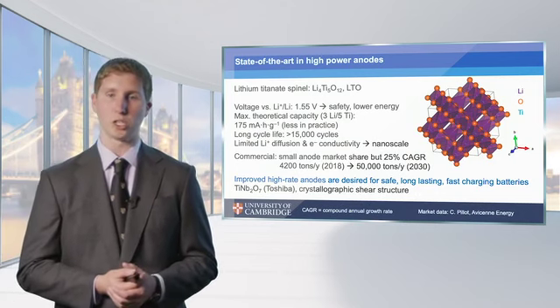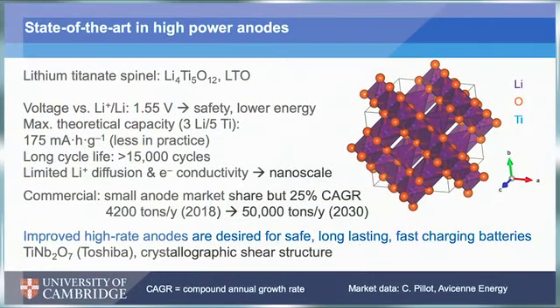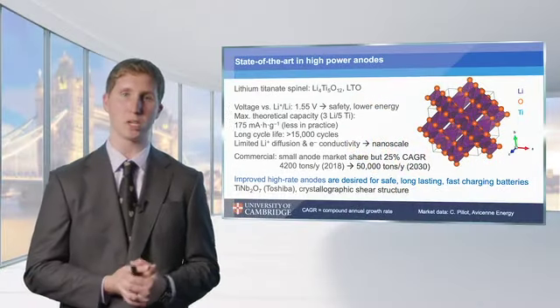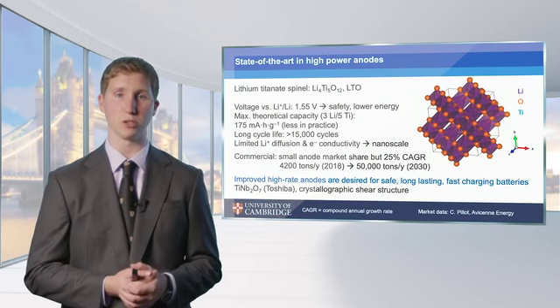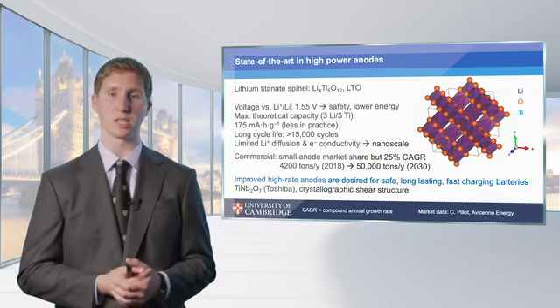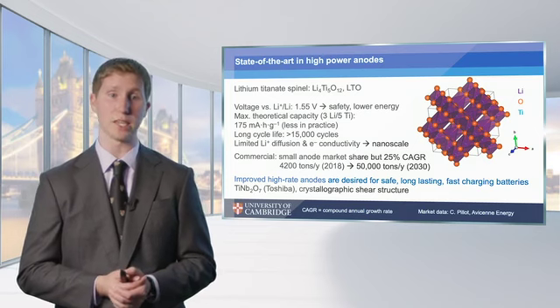Now, there is a small couple percent of the market currently which does utilize a material for high power and for fast charging applications, and that's the lithium titanate spinel. This material has a much higher voltage than graphite, and being the anode, that means it has a lower cell voltage, so we get less energy out of an LTO paired with any cathode that we use versus pairing it with graphite. There's also a limited capacity because we're not taking full advantage of the transition metals present, only utilizing the redox capacity of 3/5 of the titanium.